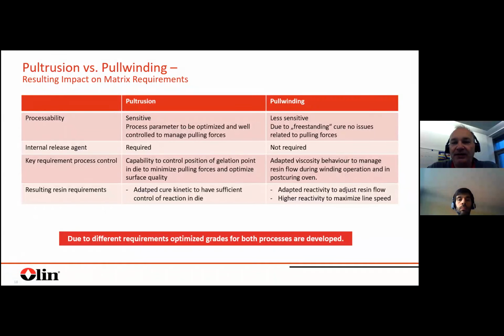In pull winding, I will go deeper into this in a minute, but at the end, you need an adapted viscosity behavior to manage the resin flow in your process at different stages. I will come to this. So what does it really mean for the resins themselves? For pultrusion, you need an adapted cure kinetics to control the reaction, to be able to establish a robust process. There are different ways to do this. I think we gave different webinars on this topic. I will not go too deep into this today.